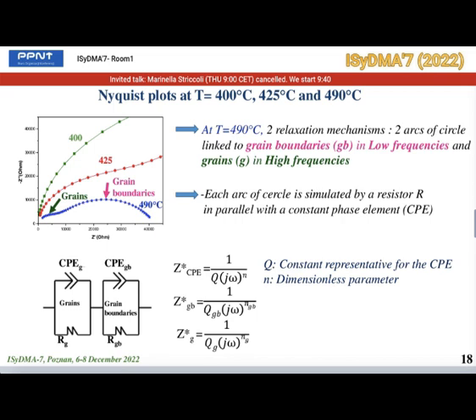Nyquist plots at 490 degrees highlight two relaxation mechanisms. We clearly see two circle arcs, corresponding respectively to grains at high frequencies and grain boundaries at low frequencies. Each arc can be modeled by an equivalent electric circuit containing a resistance R in parallel with a constant phase element CPE, represented by the Q quantity and the dimensionless parameter n. Both circuits are in series.